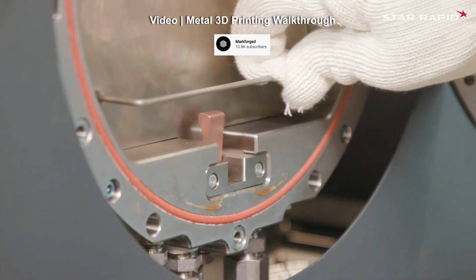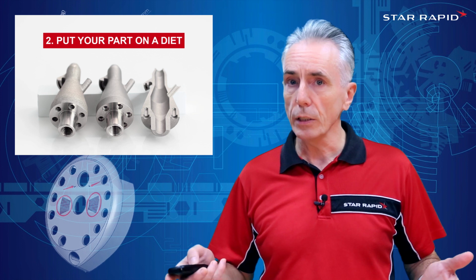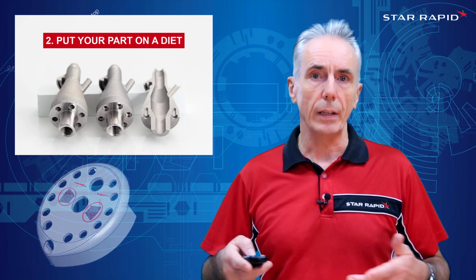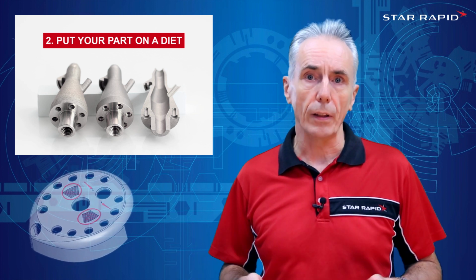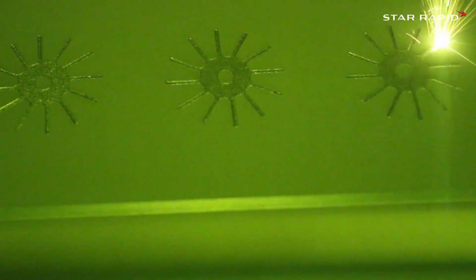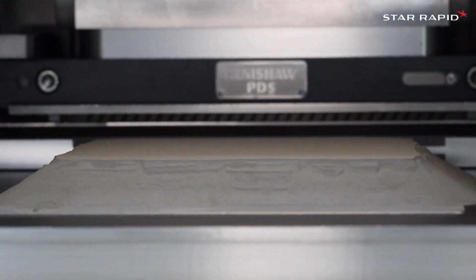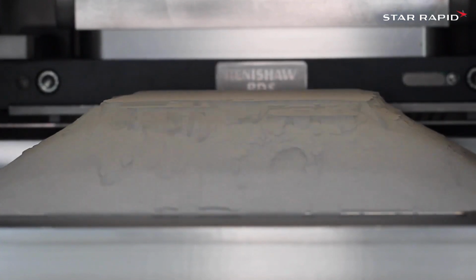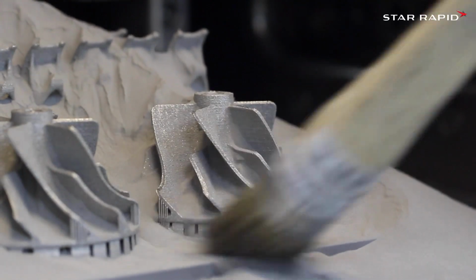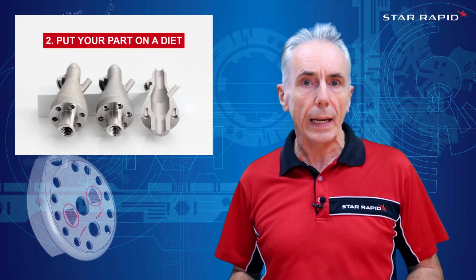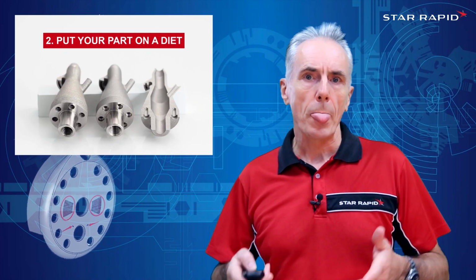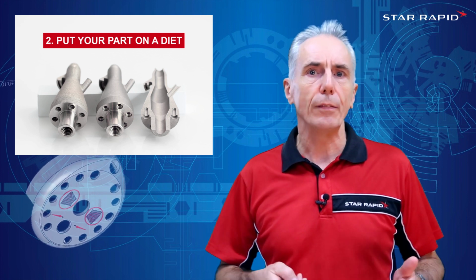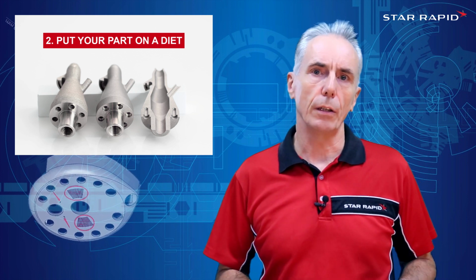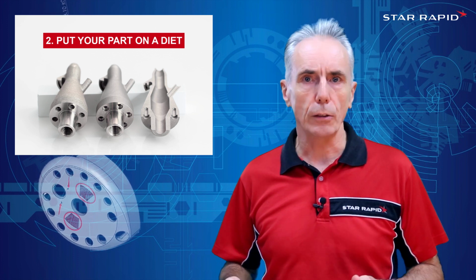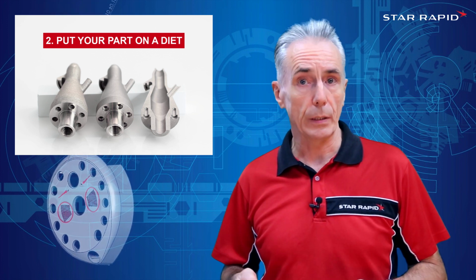This usually results in a 50% shrinkage by volume, which doesn't necessarily mean that they are inherently inaccurate, and I've personally found that the shrinkage is quite predictable. The build time for laser-based direct metal melting technologies is very closely related to the volume of the material used, and to a lesser degree to the height of the build, whereas the multi-jet printing with sintered technologies are pretty much the opposite, with height of the build being the main consideration and volume being a secondary one, except for the cost of the material itself.